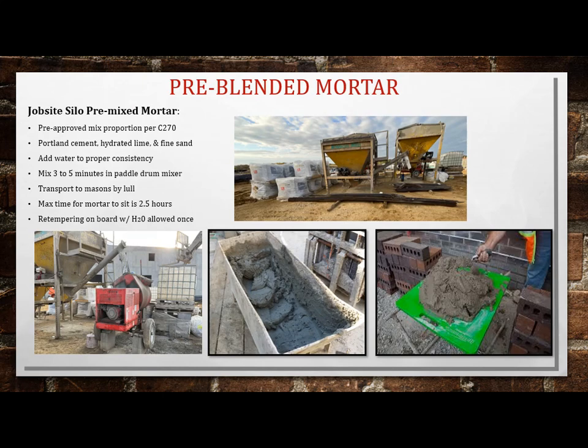Okay, so the next component, mortar. A lot of mortar today is pre-blended. It's pre-approved by proportion, so it is an approved mix design. It arrives in bags and they put it in silos. The mortar is constructed of Portland cement, hydrated lime, fine sand, and water that is added by the mixing crew to the consistency they need for that particular day and the environmental conditions they're in. It's mixed for 3 to 5 minutes in a paddle drum mixer, transported to the masons in a lull, and then construction begins. The max time is 2.5 hours you can have mortar on a board. It can be retempered once with water.